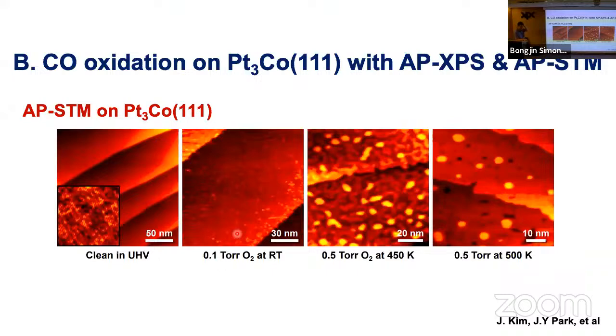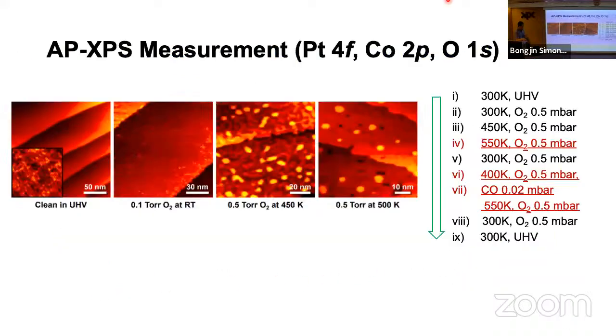So we continued our study on platinum-3 cobalt, because that's the material that is actively used in the industry. By this time we were working together. We know each other. So during this measurement, they were communicating together, and we ran basically the same experiment as platinum-3 nickel, but now with platinum-3 cobalt as the substrate. I will explain this one later. So first,